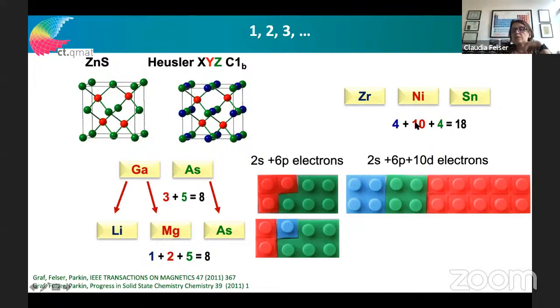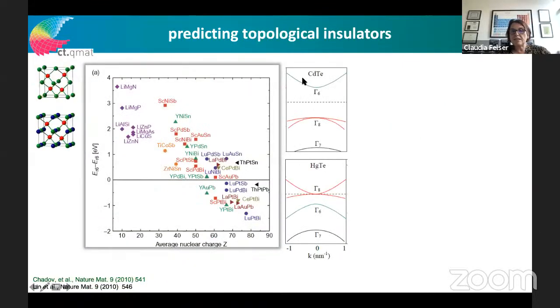And many thermoelectric materials are topological—more or less I would say all of them, because spin-orbit coupling is good for thermoelectrics, and thermoelectrics really are showing nowadays a very promising pathway, because they show very high figure of merit. So these are 18 valence electron compounds, but now you can imagine I can make the same electronic structure as Molenkamp did with the quantum spin Hall effect in cadmium telluride and mercury telluride, also with 3 elements.